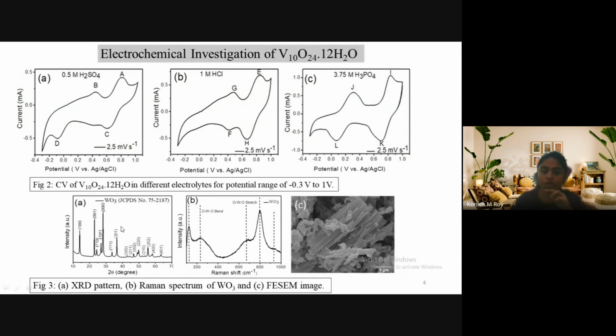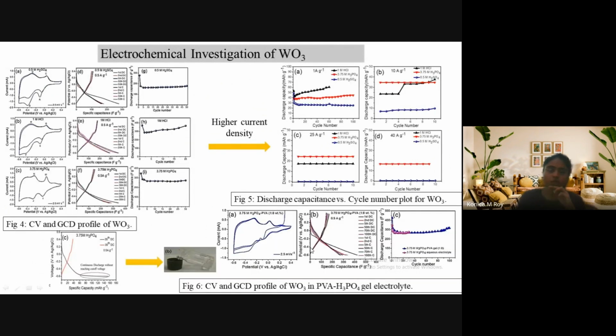For the anode material, we have chosen tungsten trioxide, which is also prepared using the hydrothermal method. It is in the hexagonal phase. This is the XRD pattern of the WO3 showing the hexagonal phase, and the Raman peaks match well with the literature, and it shows a flake-like nanorod structure. So this is the electrochemical investigation of WO3 in the same electrolytes, taking the same proton concentration.